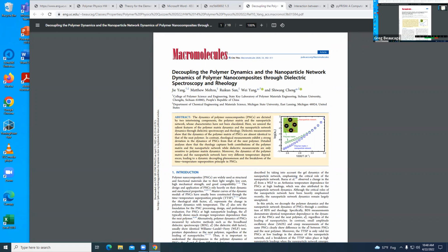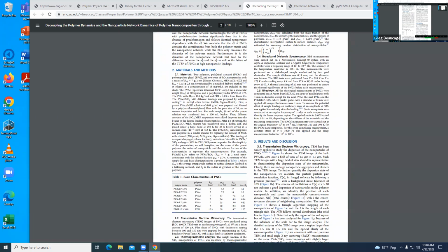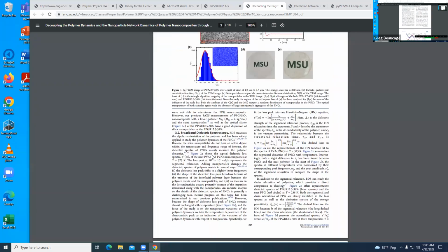This is another thing looking at, so log AT would give you this delta E number. So it's kind of looking at how that changes with temperature. So it's 1 over T, so it's an Arrhenius plot of AT to get the slope, which would be the delta E. So at high temperatures, the polymer matrix dominates. At low temperatures, you get this combination of the matrix and the nanoparticle thing. So there's this transition region. He references this paper too. It's kind of important to his theory.